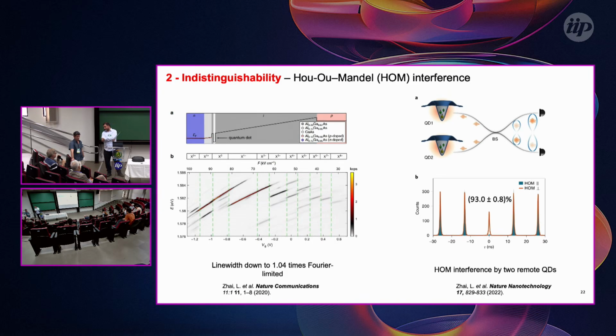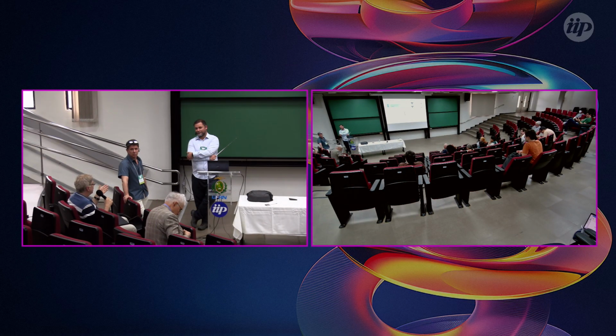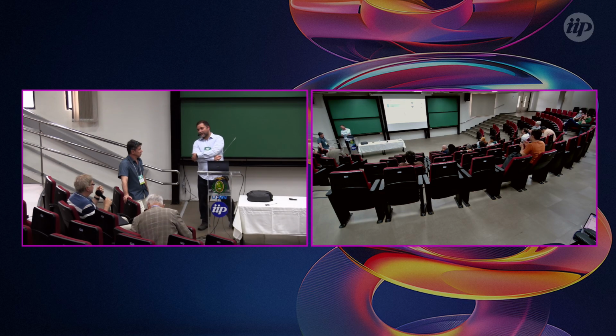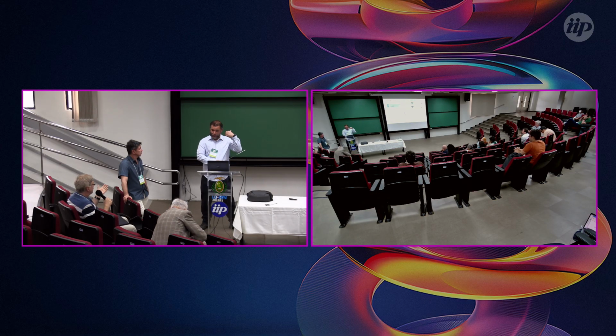In general there are also more problems, because it's hard to find dots that have the same, for example, fine structure splitting, understand? This is my next question: you mentioned fine structure splitting. How is it compared with the line width? It depends if you are a good grower. In general, the line width of these quantum dots is around 3 or 4 microelectronvolts. But you can grow these quantum dots with, let's say, a small distribution.